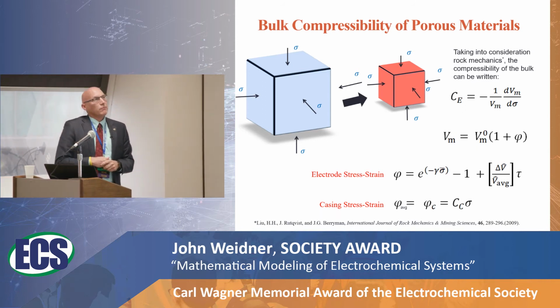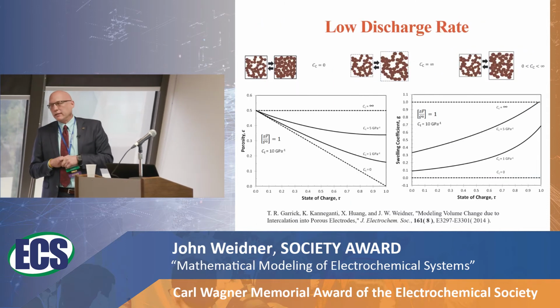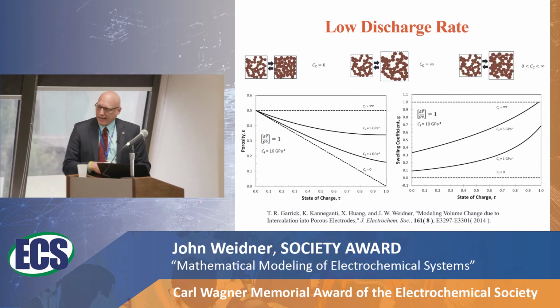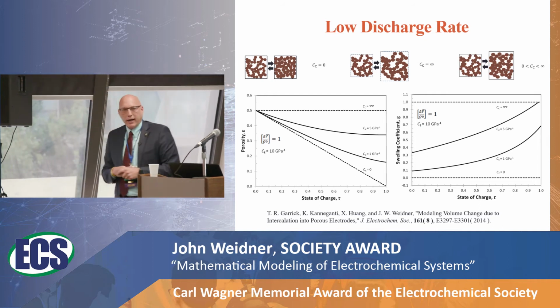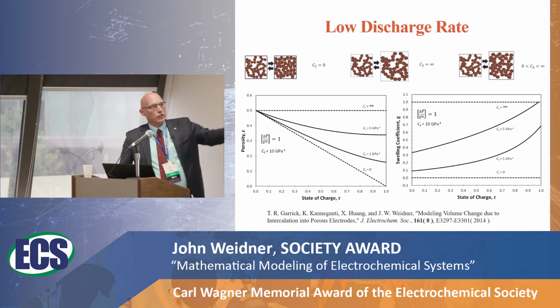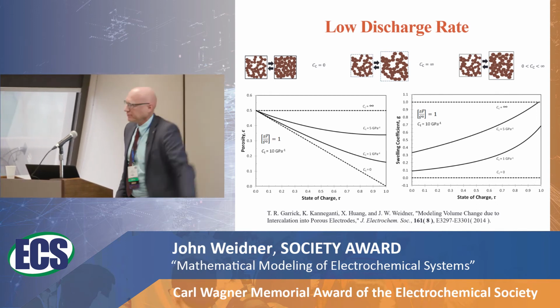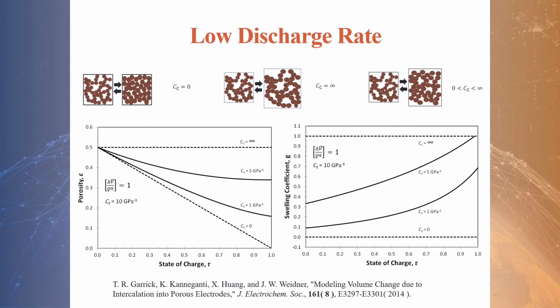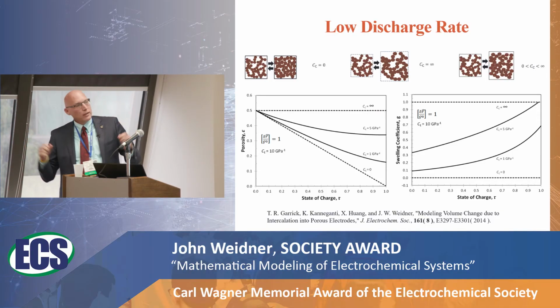So here's some examples of that. And here is a low rate discharge, meaning everything is uniform. And again, another nice thing about modeling is you can do things that maybe aren't, quote, physically realistic. So this is a battery that only has one electrode. But we can, again, at least understand what's going on before we expand it into an actual cell. And so here is the example where the can will not expand. So it's a very, very rigid can. And therefore, when those balls expand, they just fill the porous region.